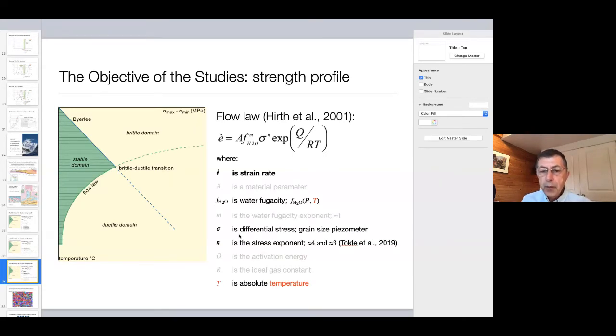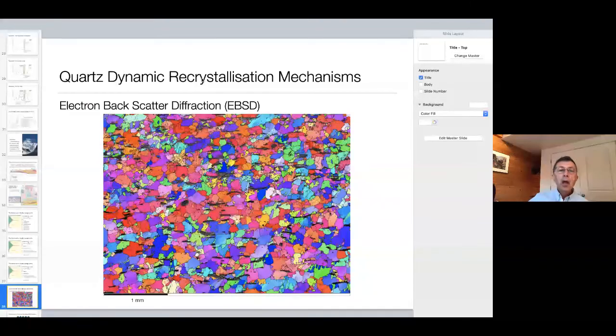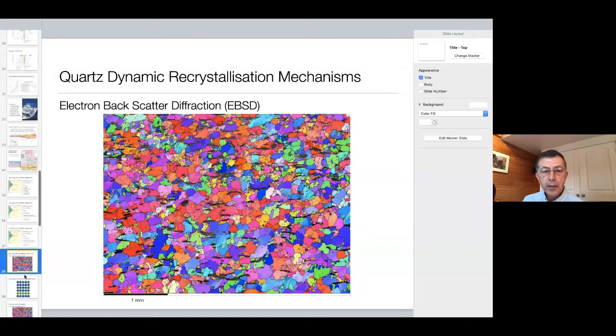The next thing we have to determine is the stress, the differential stress or the flow stress. To do that, we use the quartz dynamic recrystallization mechanisms, the shapes of the grains, to tell us what the deformation was. Here we are looking at a micrograph, here's 1 millimeter for the scale, obtained by electron backscatter diffraction, EBSD, where the colors show the crystallographic orientations. At the same time, this type of imaging allows us to very precisely map the grains and subgrains. So this is a much more precise analysis than optical analysis.